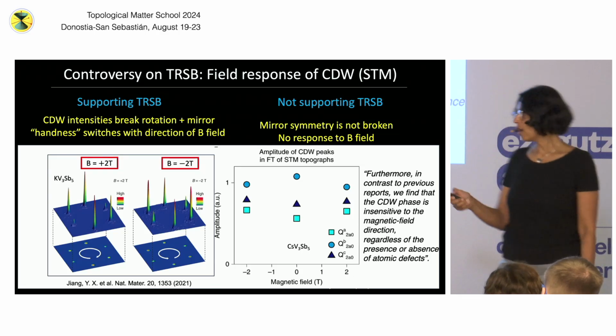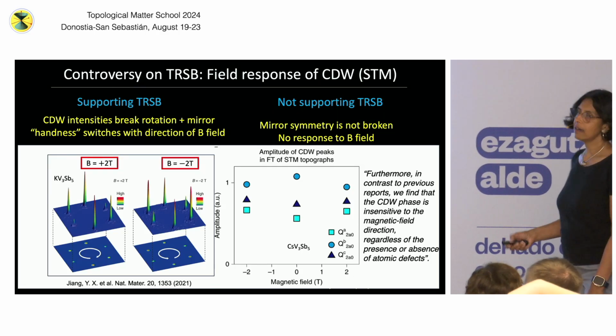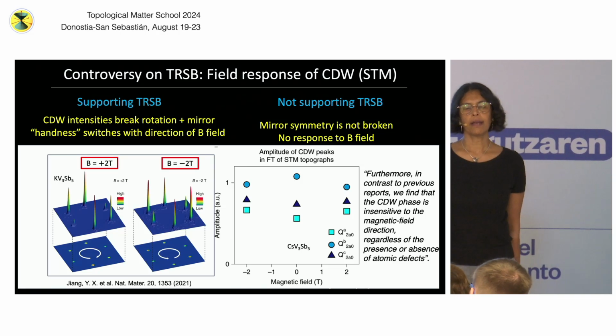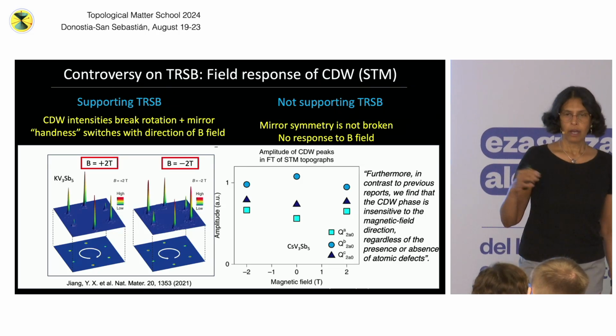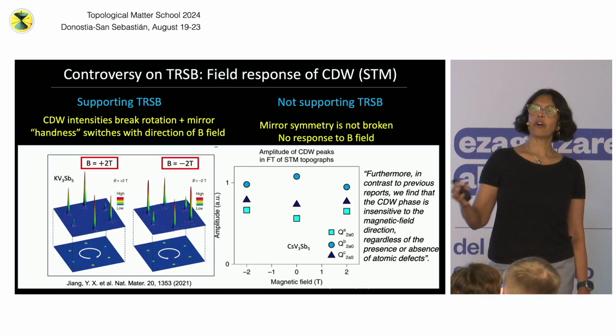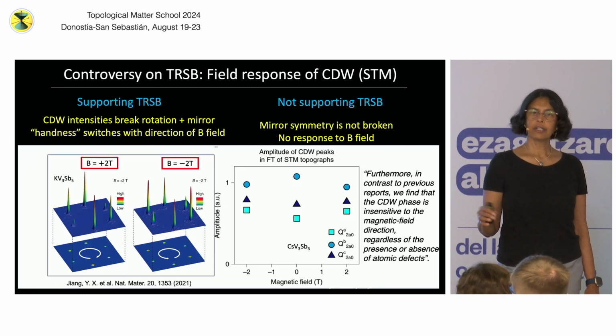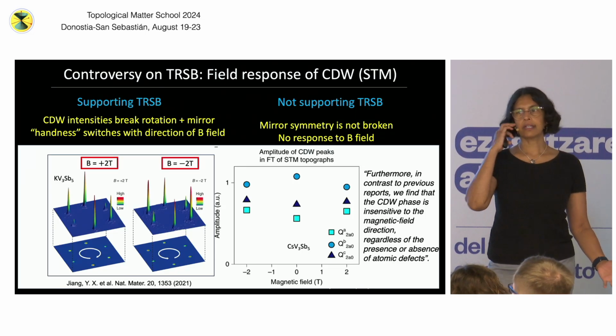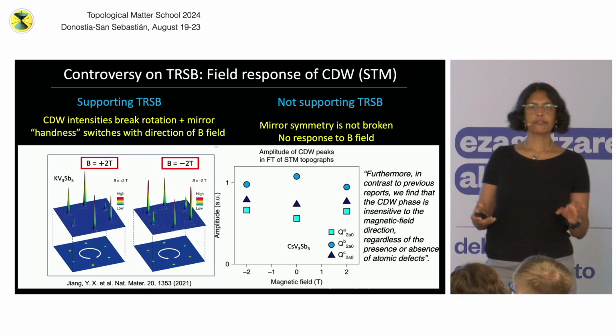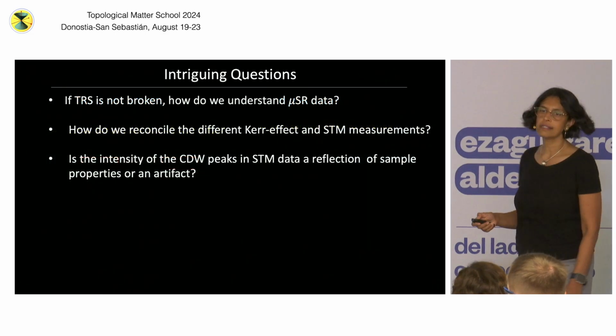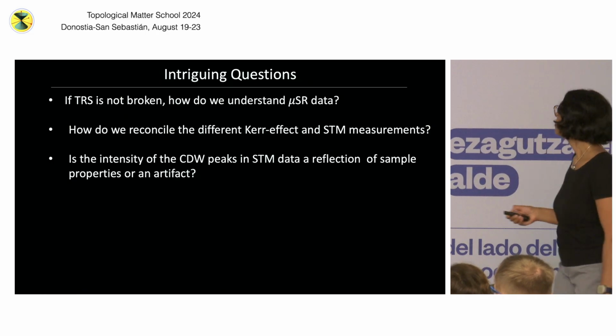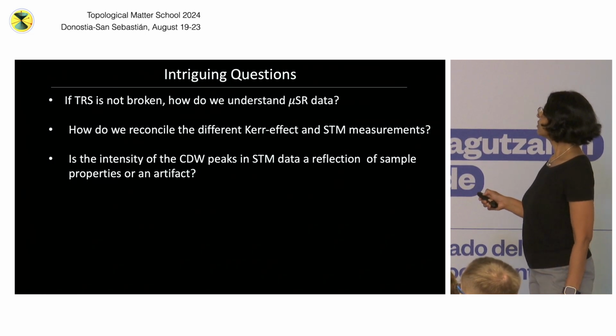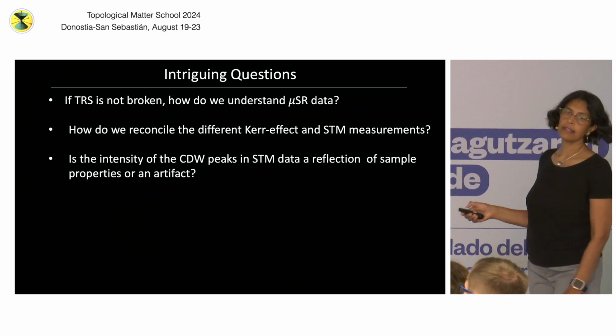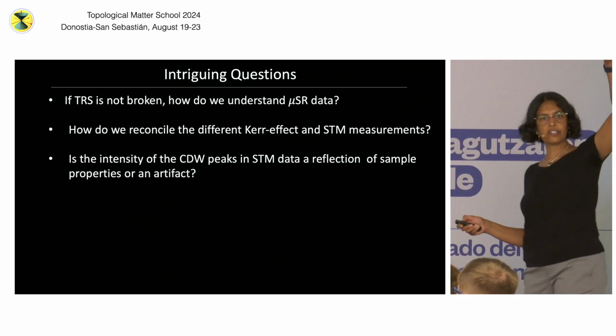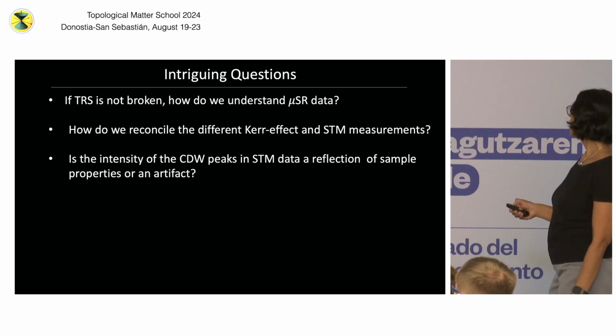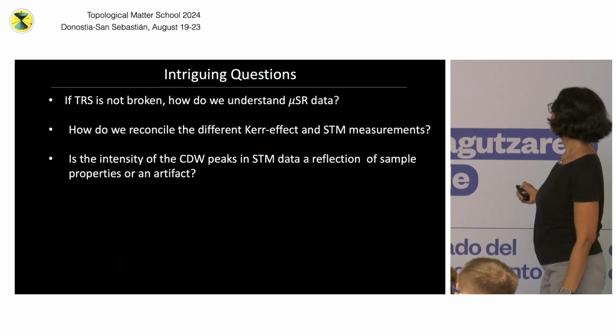In any case, so conflicting STM data, I'm not showing it here in the interest of time, but also conflicting Kerr effect data. Kerr also measures broken time reversal symmetry. One group sees broken time reversal, another group doesn't. So huge amount of conflict, so there was no consensus on whether time reversal is broken or not. So then here are the questions. If time reversal is not broken, how do you understand the mu-SR data, that increase in the relaxation rate below a certain temperature? How do you reconcile Kerr effect and STM measurements?